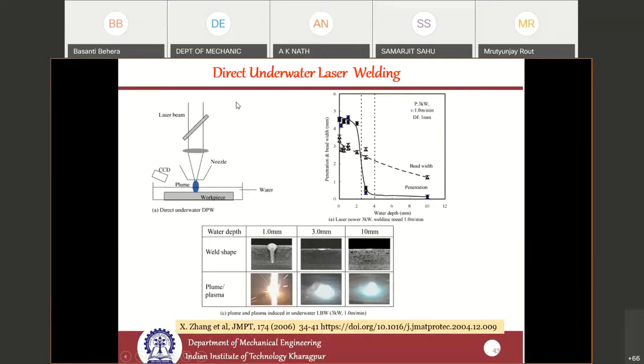This is direct underwater laser welding. Up to a few millimeters inside water, you can directly do the welding and get very good quality keyhole welding. But if you go beyond 1 or 2 millimeters, you find that the laser beam gets absorbed and creates a lot of plasma plume, so the laser power cannot reach the surface if the water depth is more than 2 millimeters. Therefore, you get very poor welding. Up to 1 millimeter, you can get very good quality welding done.